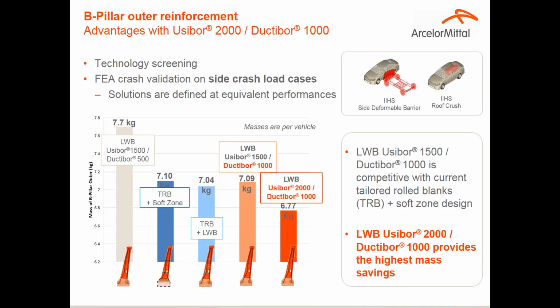What we can say now, then, are two main points. The first is that sometimes it's not needed to have a lot of thickness variations or different grades in the same applications. And sometimes a simplification of the part can bring the same results. In fact, you see that the solutions with different thickness variations are at the same level in weight as a simple application like Usibor 1500 and Ductibor 1000, but answering in the same way to a lateral crash in this specific case.